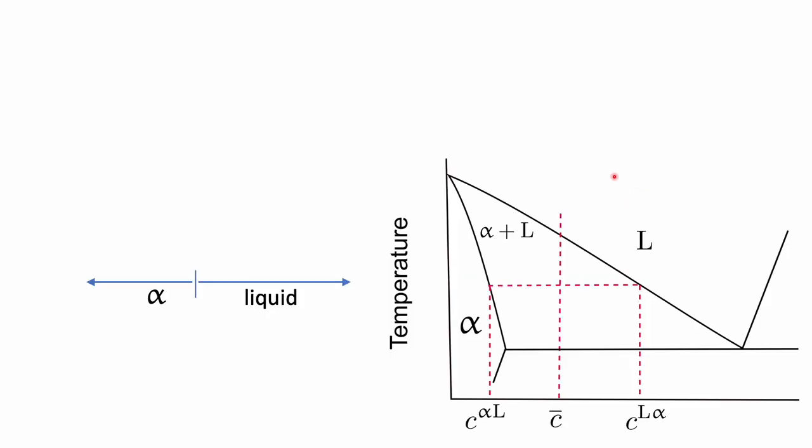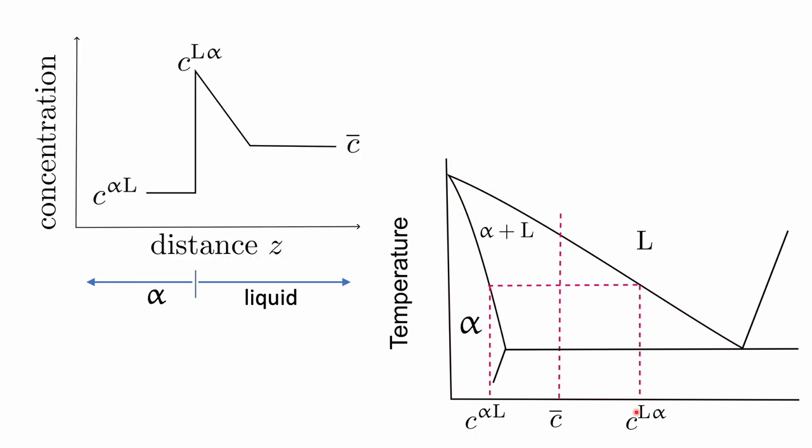Consider the growth of a proeutectic phase, alpha, from liquid of composition C bar. Now, obviously at any temperature, the alpha has a smaller solubility for solute when it's in contact with the liquid than the liquid has for the solute when it's in contact with alpha. Therefore, as the alpha grows, solute will be partitioned into the liquid, and the concentration profile that we expect at the interface between the alpha and the liquid here is as follows, where this is the solubility of solute in alpha in contact with liquid, this point here,